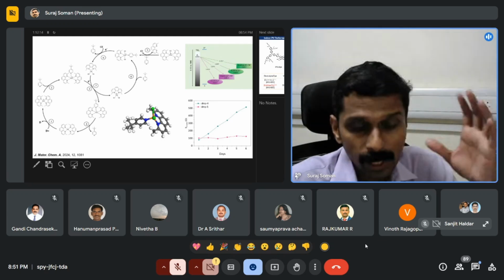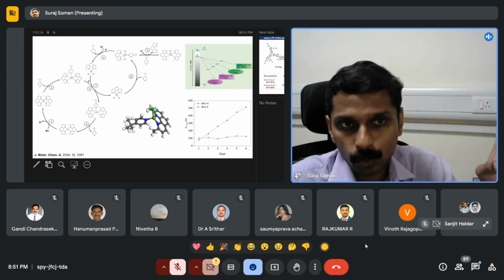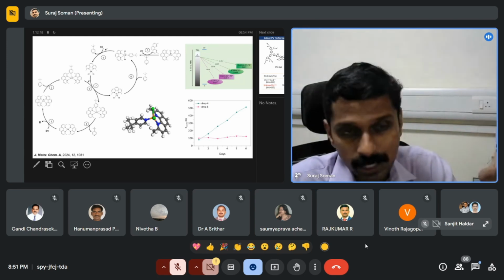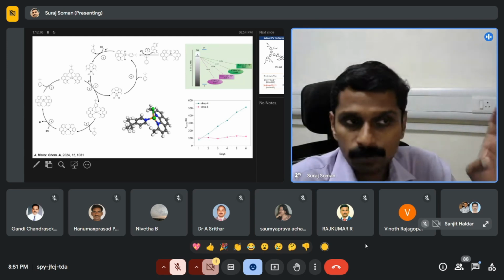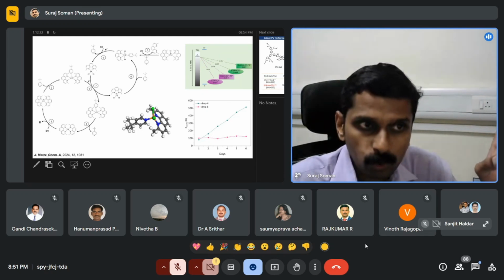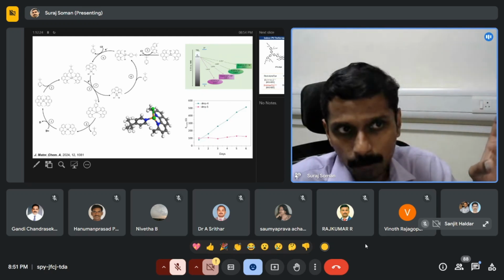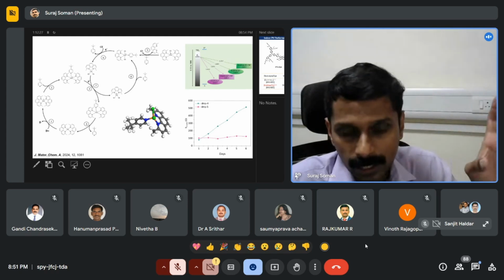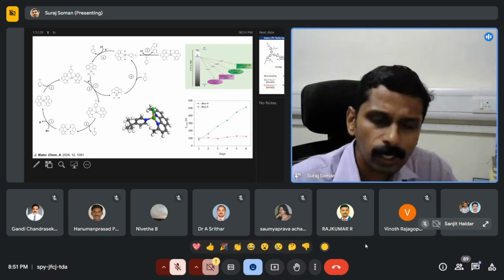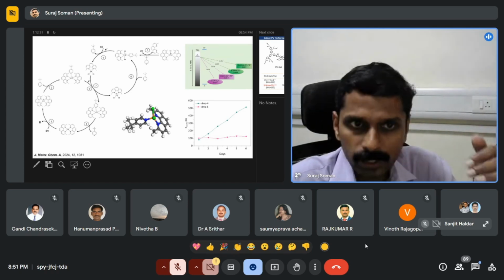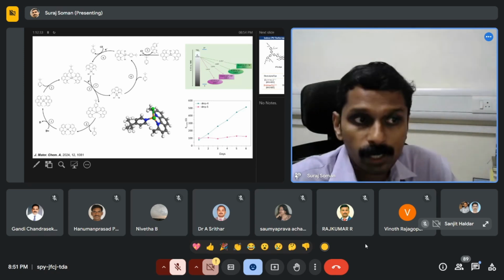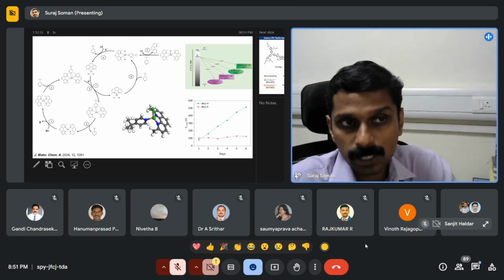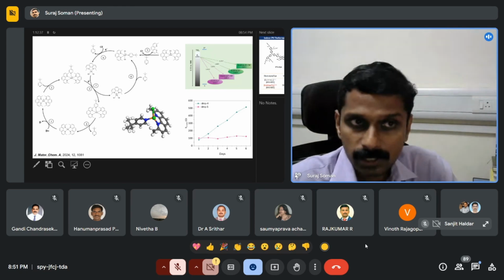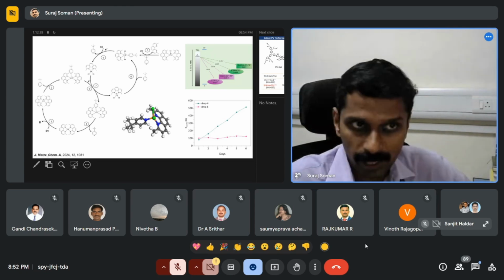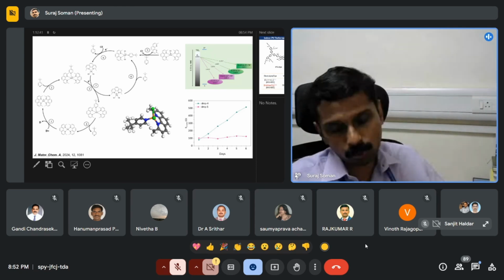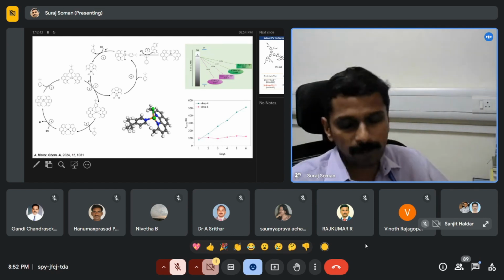And what we have observed is, normally, the oxidized copper 2 complex is very unstable. So the moment you take a conventional copper 2 complex and put it in an electrolyte, and in the electrolyte you add an additive, like tertiary butylpyridine is one additive, the moment this molecule sees the tertiary butylpyridine, it just disintegrates all the ligand, and the entire TBP gets attached to the copper. That's a known phenomenon, it's a known fact.